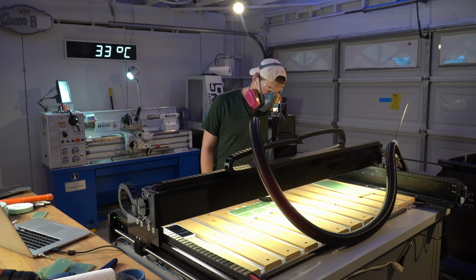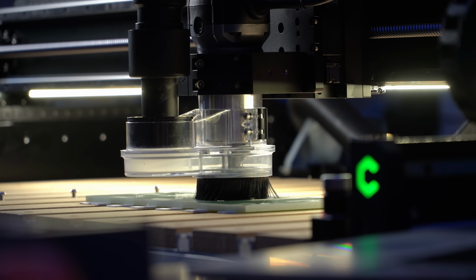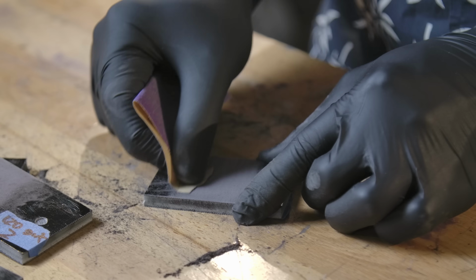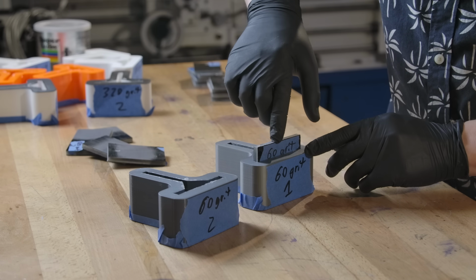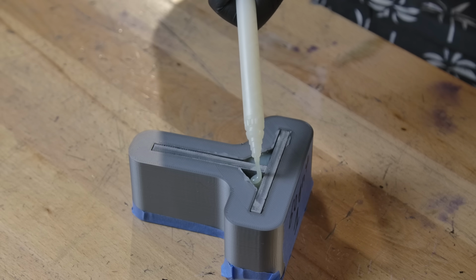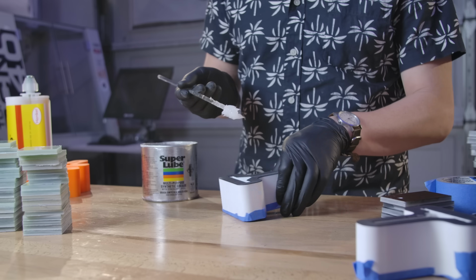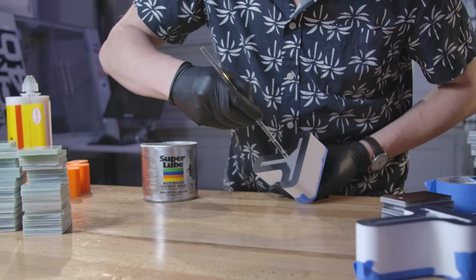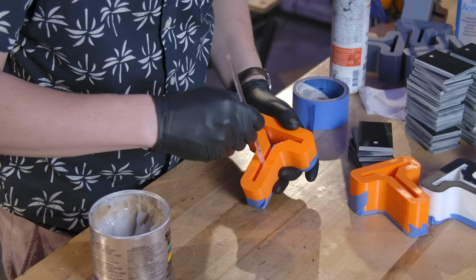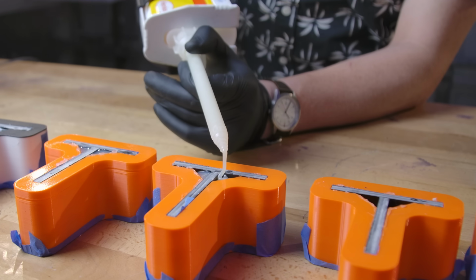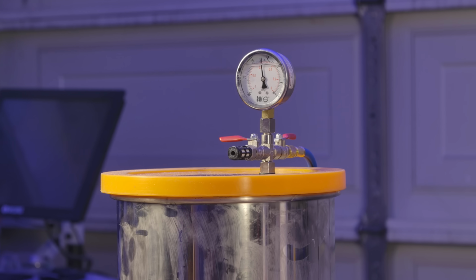I cut out 2x3-inch coupons on the Carbide 3D Shapeoko, and after bond prepping them, I placed them in 3D printed molds to allow the epoxy to form into the shape that I wanted. The molds are coated in superlube with a long stick beforehand to act as a mold release so that the epoxy won't bond with the print. After labeling each coupon and putting the epoxy into the mold, I put each test article into the vacuum chamber to remove all the bubbles I could.